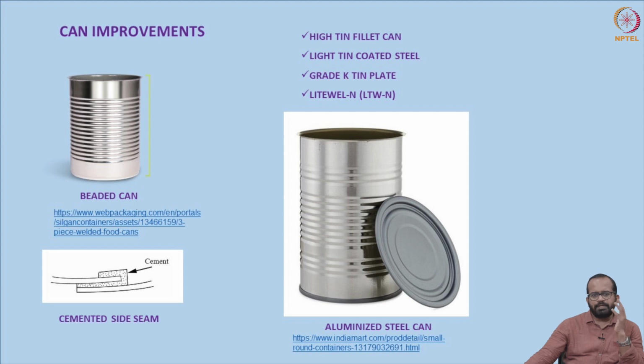And there are also Litwell N or LTWN containers. It is also a less tin container. It has a nickel alloy layer between the tin coating and steel. It gives additional corrosion resistance, weldability, and lacquer adhesion compared to tin plate. So it is an enhanced property compared to normal tin plate.